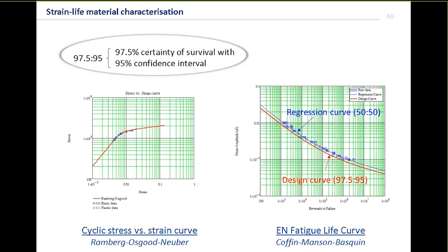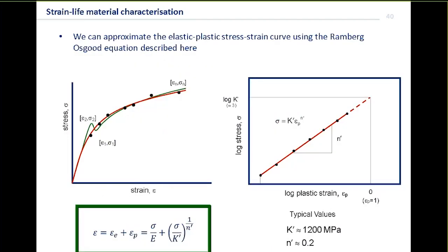So how do we fit the cyclic stress strain curve? Well, we use a simple approach. It's an equation, a model called the Ramberg-Osgood-Neuber flow rule. So if we were to plot the stress strain through the linear and the nonlinear range, we can start to see it follows either that red or that green line. And what the Ramberg-Osgood model does is try to fit a simple equation through that.